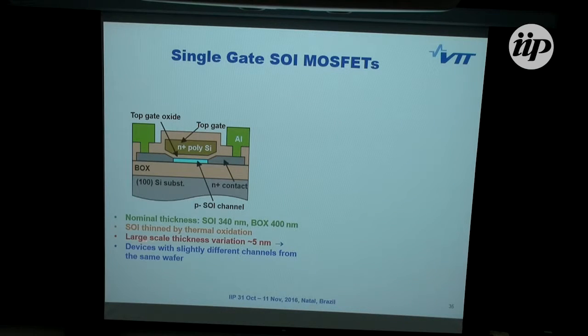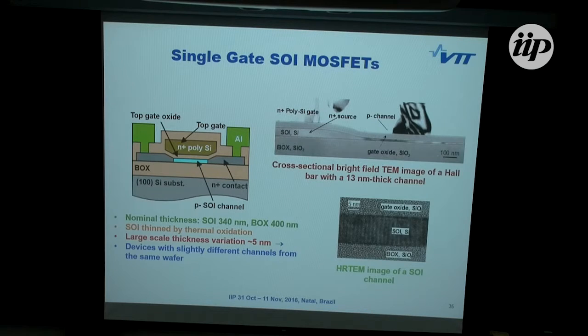And then, because the original wafers which have this SOI thickness, it's not all across the wafer, it's not 340, but it is 340 plus minus 10 or something. So it means that in one wafer we have a nice set of samples with different channel thicknesses. And a real device looks something like this. So we have the buried oxide here. This is the silicon channel. This is the contact part, which is highly doped. And then this is the channel. This is the gate oxide, and this is the polysilicon gate. And this thickness we vary from device to device.